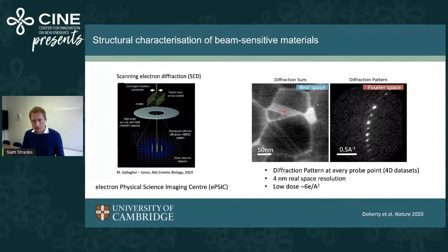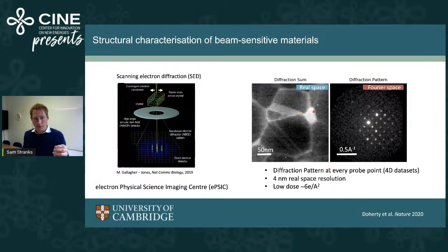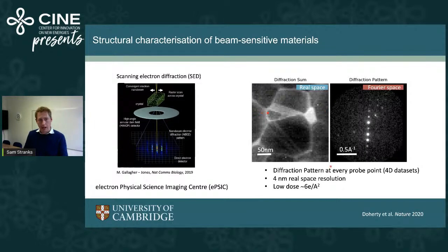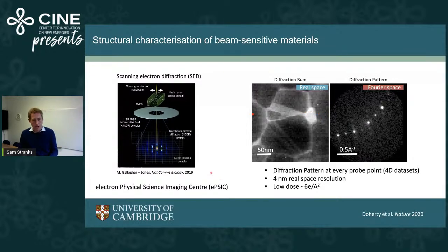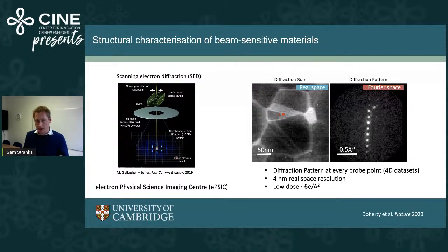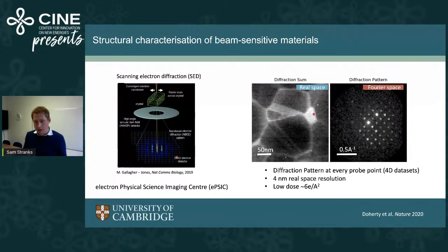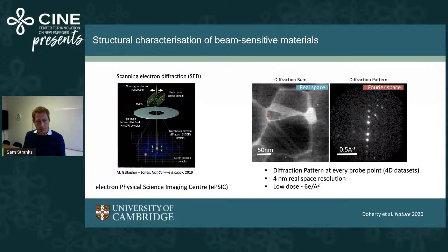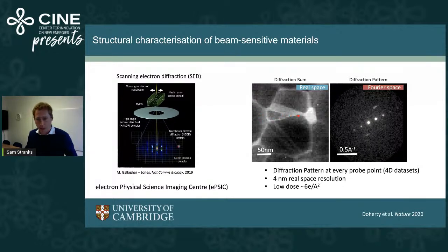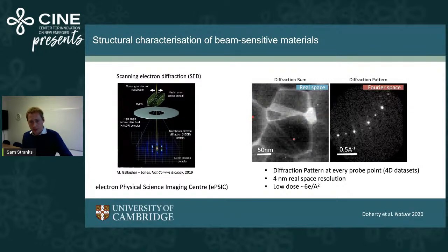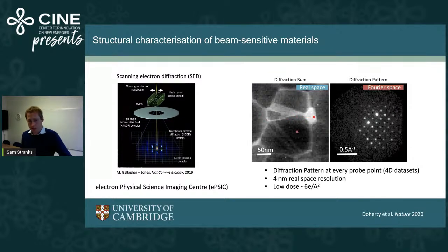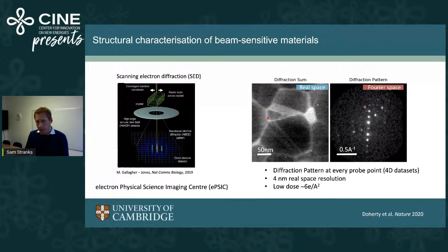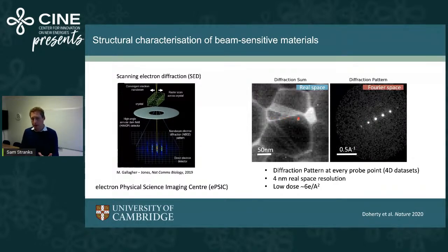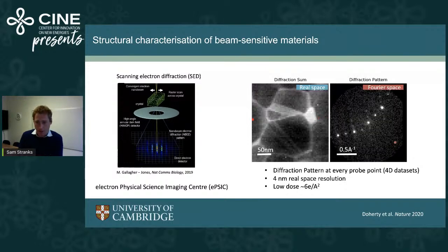So I want to introduce one more technique, and this is now, to zoom in a bit further, looking at electron diffraction. This is a scanning electron diffraction measurement. This is really useful. This is actually done at the ePSIC facility near Diamond in the UK. And here we have a direct electron detector, and this is important because it means we can go to very low doses of electrons, which is very important for these beam-sensitive materials, to get good information without damaging the sample, or without at least worry of damaging the sample. It's a very powerful technique because we can get a lot of information from this. This is a sum diffraction image from this scanning electron diffraction. And on the right, this is showing the full diffraction pattern from each of these points. And so we can get a lot of information about the structure.